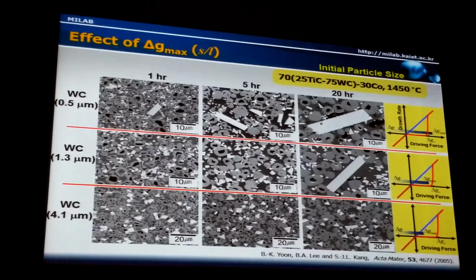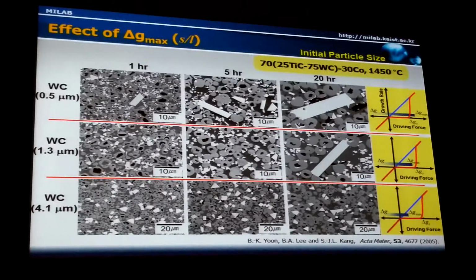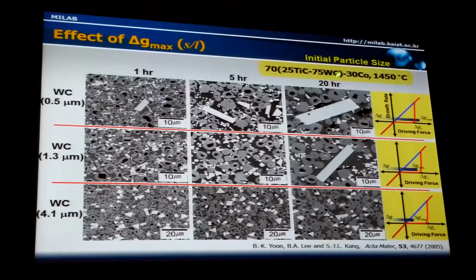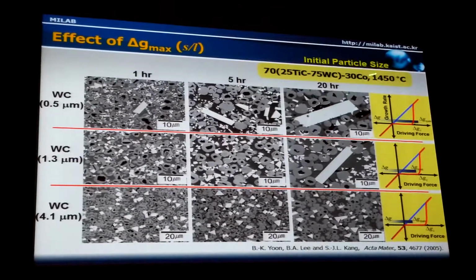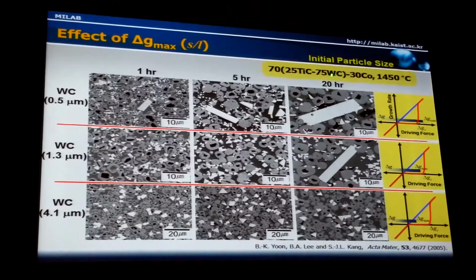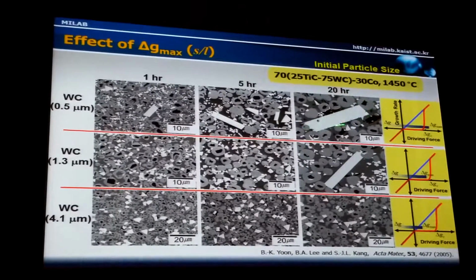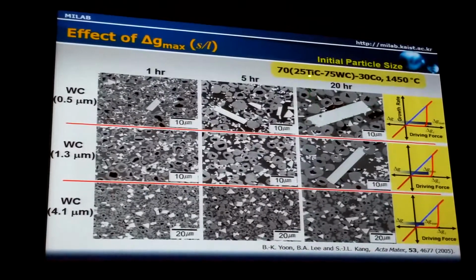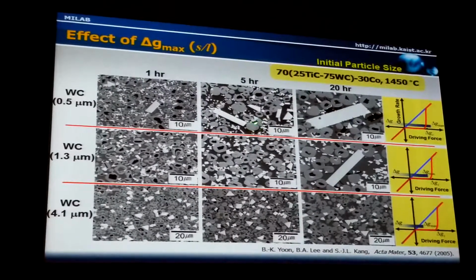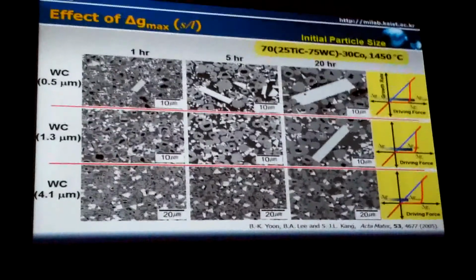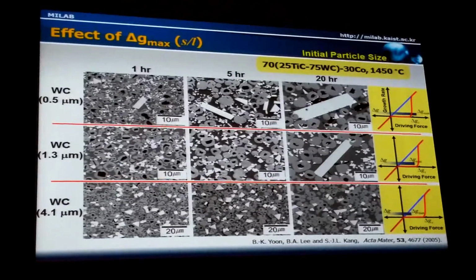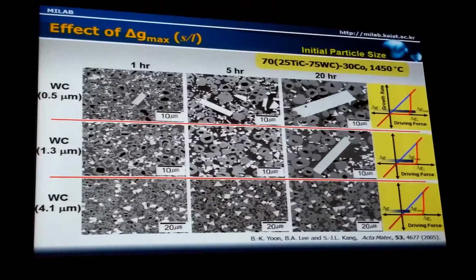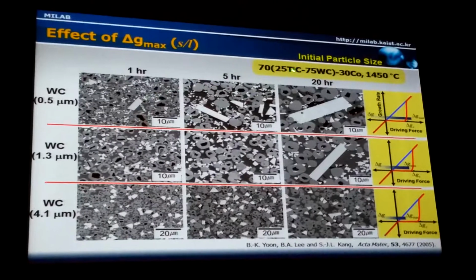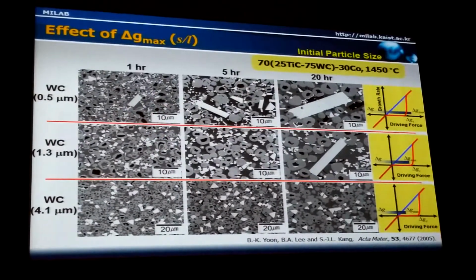And this is another example that shows the effect of the maximum driving force. We took the titanium carbide, tungsten carbide, and cobalt system. Cobalt forms a liquid, the dark area, and tungsten carbide grains are the faceted white areas. Titanium carbide grains are the gray areas, rounded grains. In this particular sample, we have two types of grains, faceted and rounded, in the same liquid matrix. But the grain growth behavior is totally different. Rounded titanium carbide grains grew continuously.